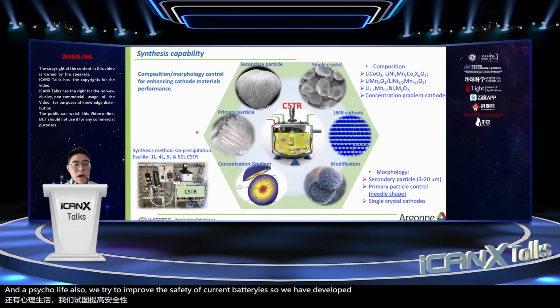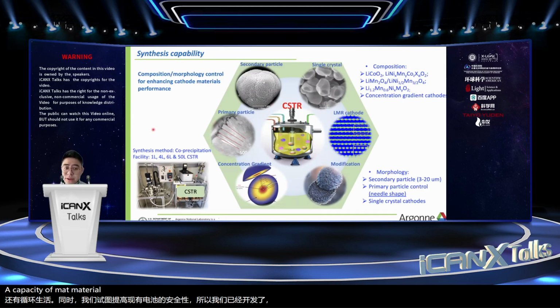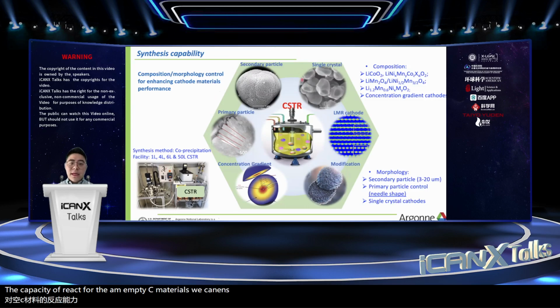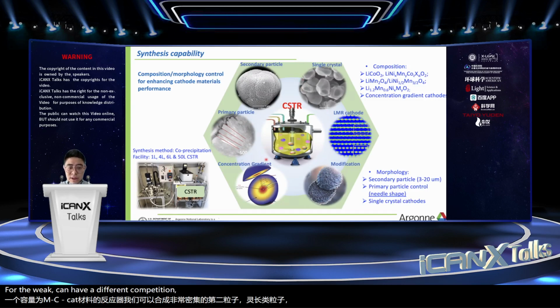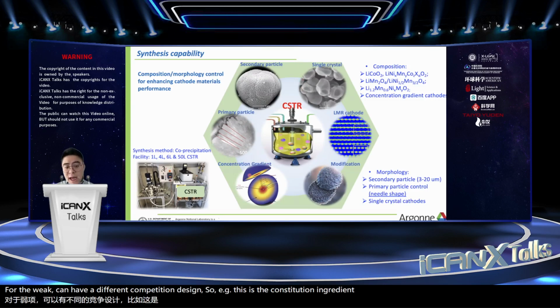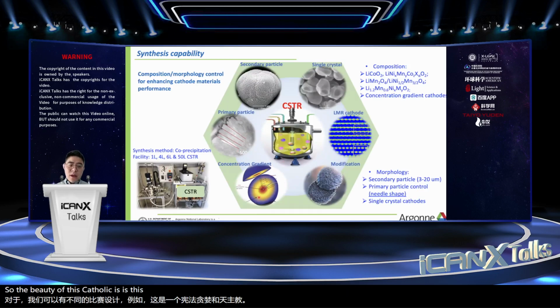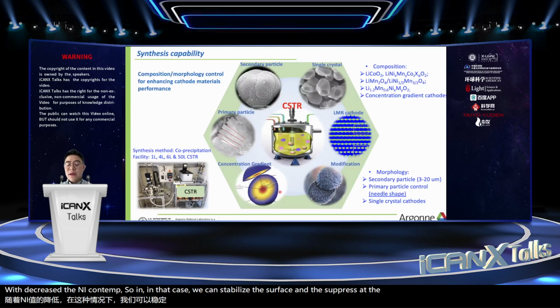So we have developed 4 capacities of material synthesis. We have different capacities of a reactor for the NMC cathode materials. We can synthesize very dense secondary particles and primary particles. Further, we can have different composition designs. For example, this is a concentration gradient cathode. The beauty of this cathode is that we have different compositions within one particle. In the particle bulk, we can have very high nickel content to deliver high capacity. And then toward the surface, we decrease the nickel content. In that case, we can stabilize the surface and suppress the surface side reactions.